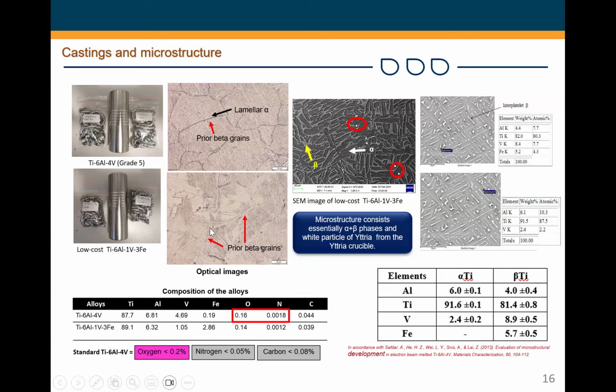And we carried out compositional analyses, and this was done at Scroobies, and we were able to confirm that the amount of oxygen and nitrogen in the alloys was lower than the standard that you would have. So we were happy with that result, because if we had oxygen content more than 0.2% and nitrogen more than these values that we have here, 0.05%, that would be detrimental to the mechanical properties of the alloy. So we were able to keep the oxygen, nitrogen, carbon content below the standard requirement, which is good. And we achieved this both in the commercial grade and of course the experimental alloys as well.